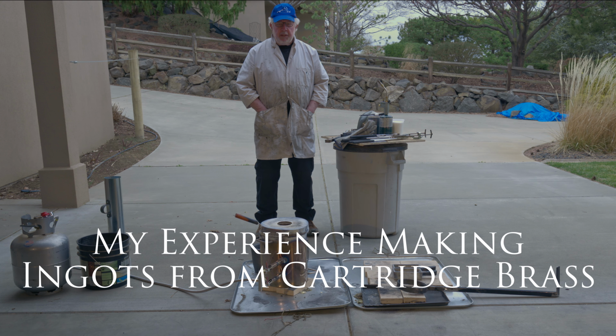Taking some of the graphite powder, I just put a little on a brush, and then dab it on the bottom, or the brick in the bottom of the furnace. And we'll take some brass and put it in the crucible. Now this crucible will hold about 10 kg, 20 pounds, 22 pounds.